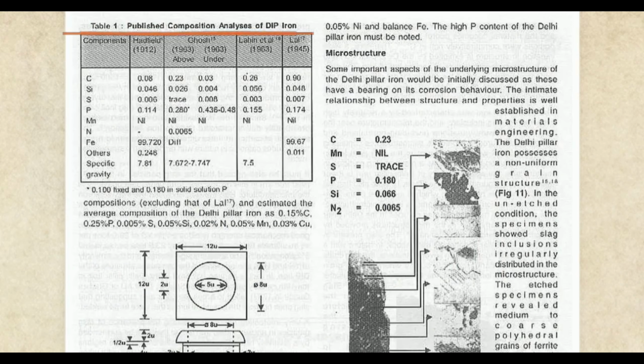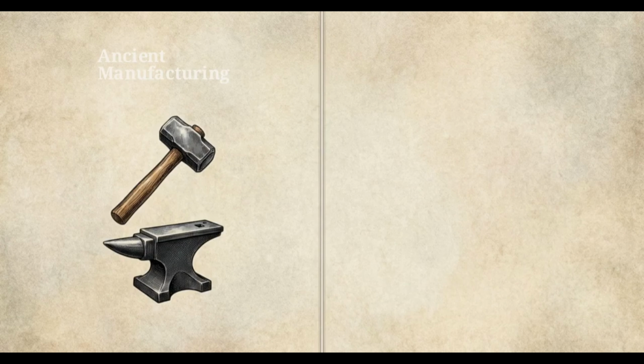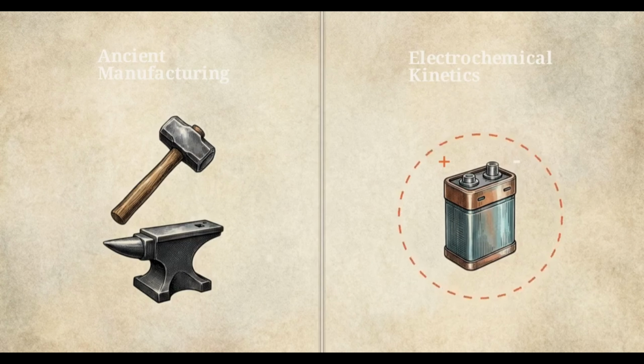This table details the chemical composition of the pillar's iron. Phosphorus levels sit between 0.114 and 0.28%, significantly higher than modern forged iron. Moving down the table, modern alloying elements like manganese and sulfur are recorded as nil or trace values. The pillar's longevity is driven by the intersection of ancient manufacturing methods and mixed potential electrochemical kinetics.